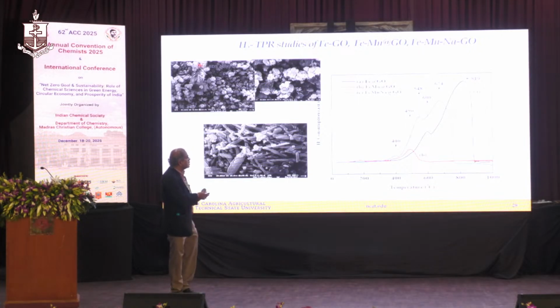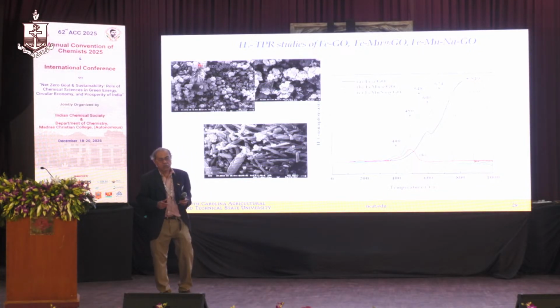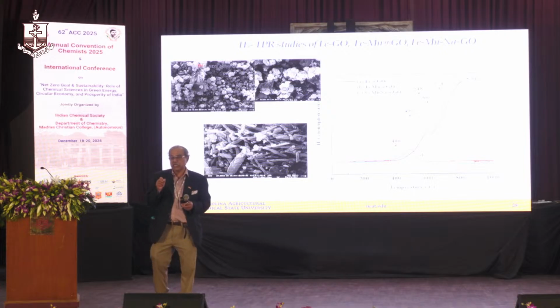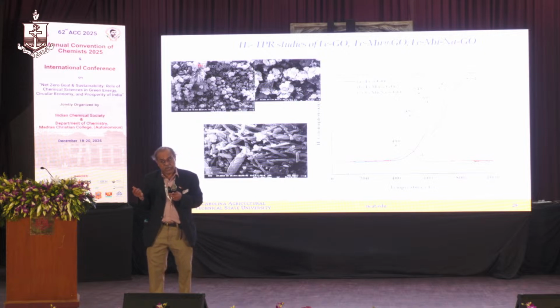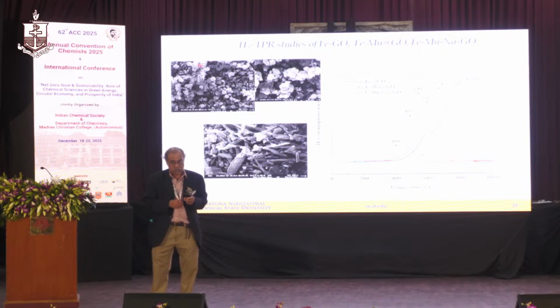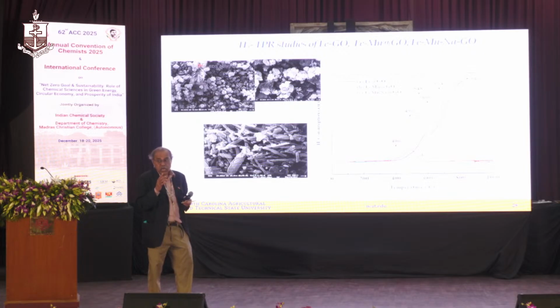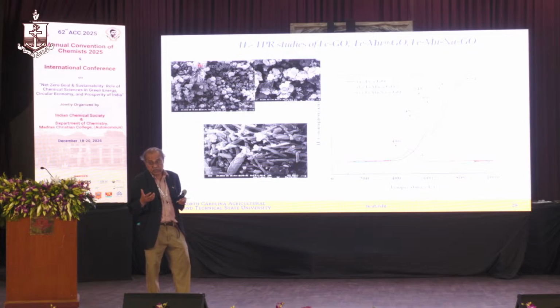Now this is called the hydrogen TPR. What it stands for: temperature programmed reduction. Now why do you do that? Because when you are trying to do any reaction, it is the reduced metal which is active in the Fischer-Tropsch synthesis. So if you use the hydrogen, you can reduce it to the metallic form, which actually forms the carbide with the CO, and that is the active species for catalysis. So you do this just to see what temperature you should use to prepare your catalyst, the final species.